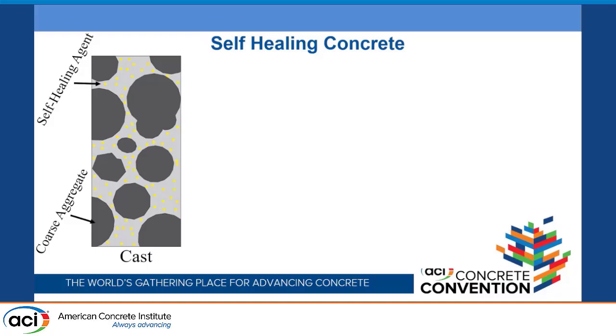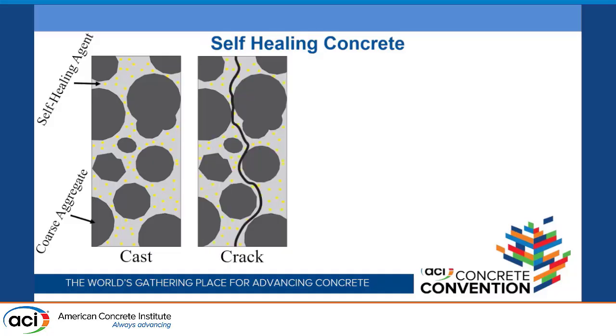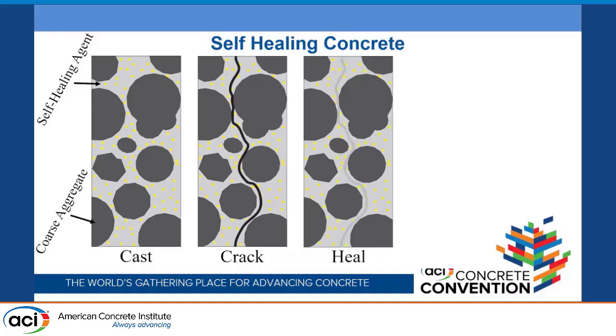It's not the most complex methodology, but it works relatively well, where you're just going to add your self-healing agents into your mixture, disperse it evenly throughout, and eventually, when concrete cracks, it'll form along a pathway, and you'll rupture your self-healing agents along that pathway. As moisture ingresses into that system, the crack will begin to heal as precipitates form. Typically for bacterial and most other self-healing agents, it's going to be calcium carbonate forming, but there are some other precipitates as well.